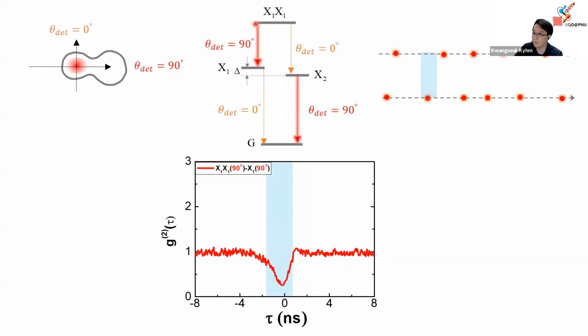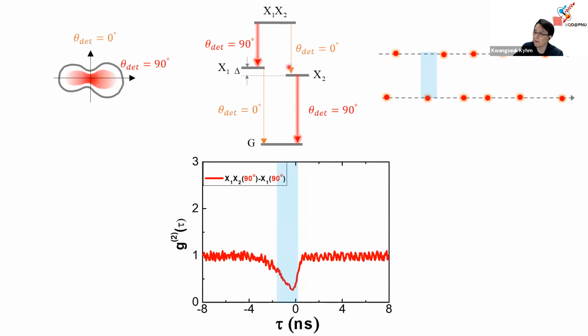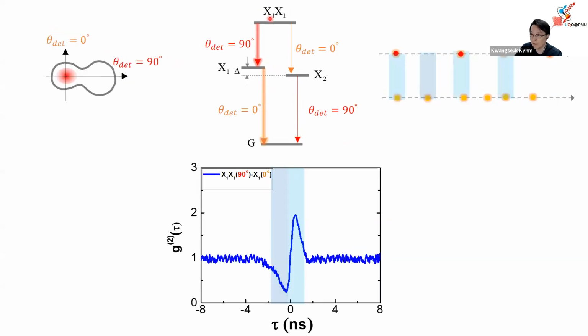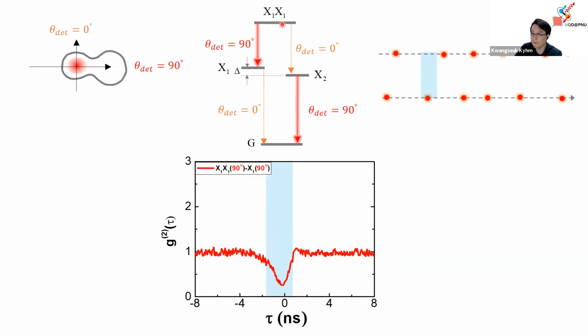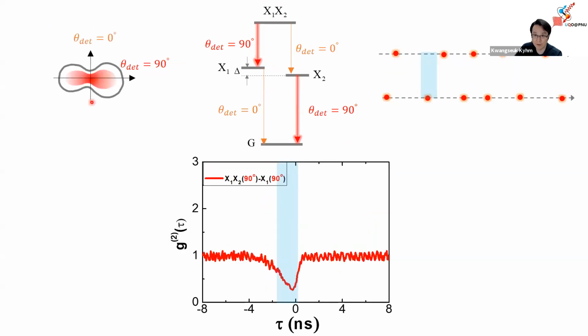On the other hand, if you do the cross correlation between these two, 90 and 90, it only shows anti-bunching. So these two are independent sources. Okay. And again, this is not local biexciton, it's coupled biexciton. Here, in the former case, it was a local biexciton, X11. But this is coupled biexciton, which consists of excitons from two different dots. So coupled biexcitons also show cascade emission to the different excitons, X1 and X2.